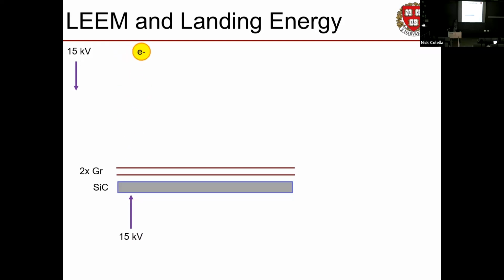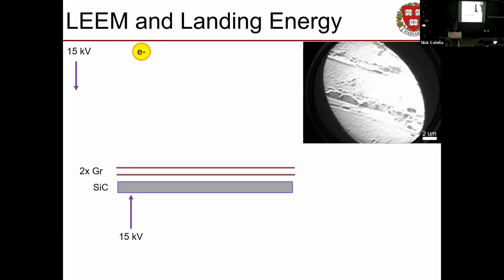Bounce. That happens. Here we go. Bounce. It bounces because they're exactly the same energy, 15 kilovolts in both cases. The electron doesn't even really touch the sample. It slows down before it even hits it. But okay, it interacts with it somehow. The edge of the electron's wave function touches the sample, and so we get some sort of texture in our picture, and it looks like this. It's kind of a mess, but okay, there's some sort of picture, right?